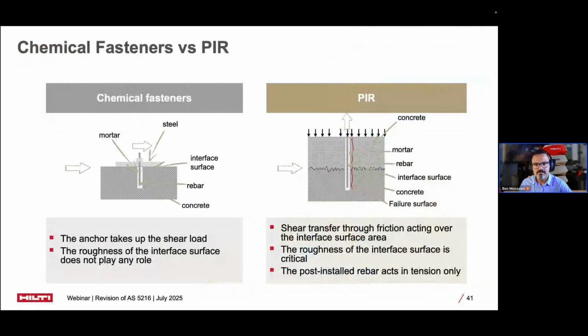Understanding post-install rebar requires distinguishing it from chemical fasteners. Chemical fasteners connect a steel fixture to concrete, with the anchor taking up both tension and shear loads directly. The interface surface roughness doesn't significantly affect performance.